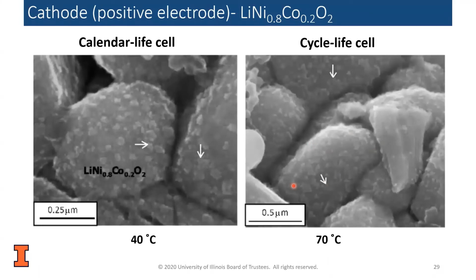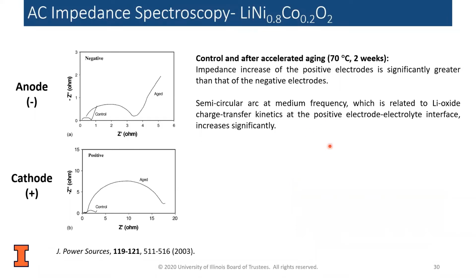And that's correct. And so if we look at the electrochemistry of the controlled aging, we can see that much of the impedance increase is actually at the cathode. Okay, and then at the anode, we'll see that both mass transport and charge transfer contribute to impedance. So this is pretty much like case 3 of the 3 examples I showed earlier. And at the cathode, this is case 1, where you're becoming charge transfer limited. You can't actually get the electrons back into the battery again. And so then if you look very closely right down here, you actually see the double semicircle appearing. So that's the case 4 I showed you.